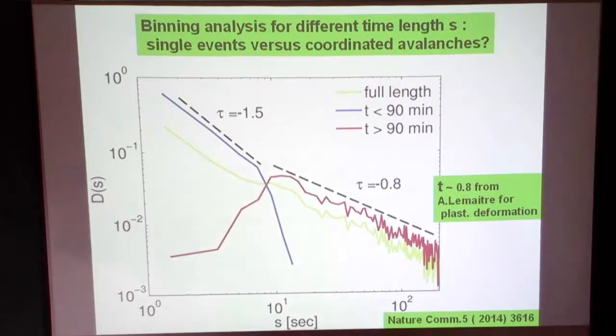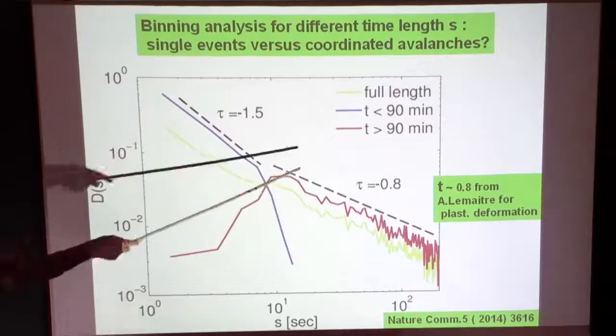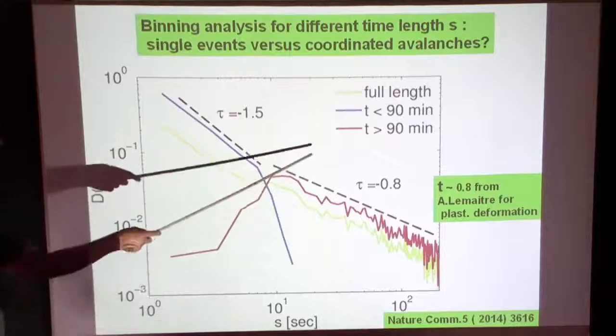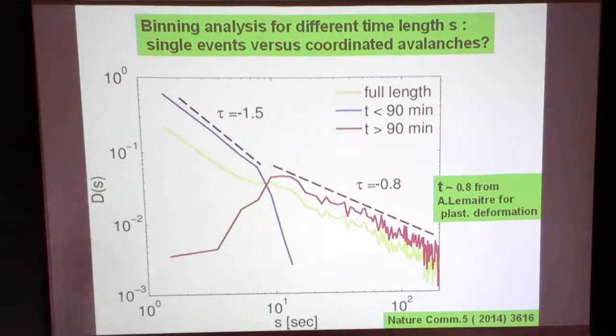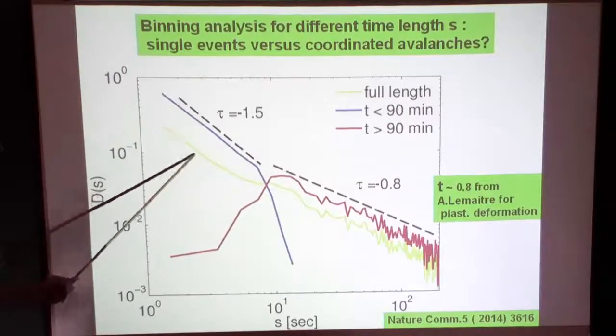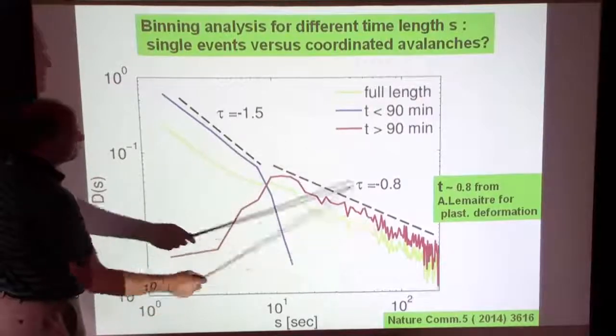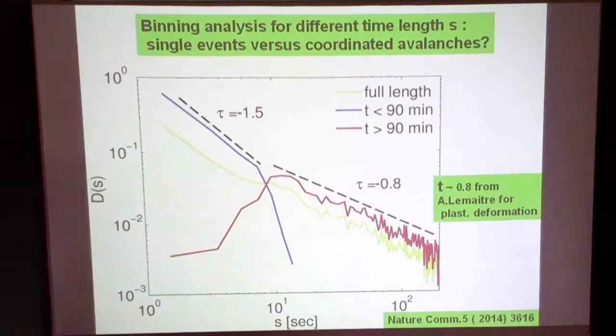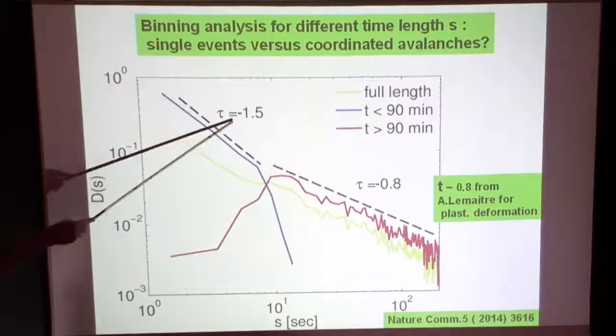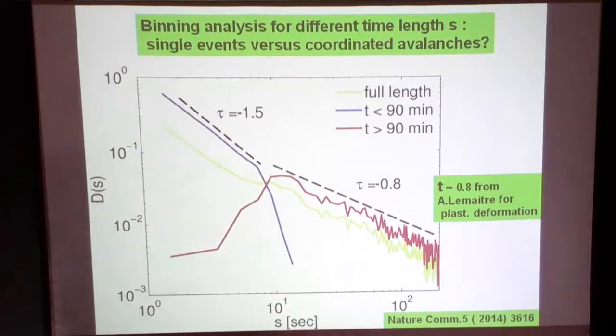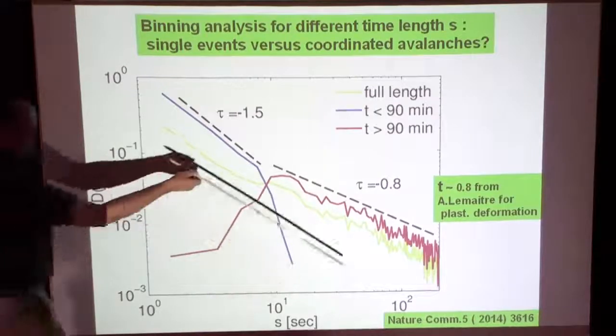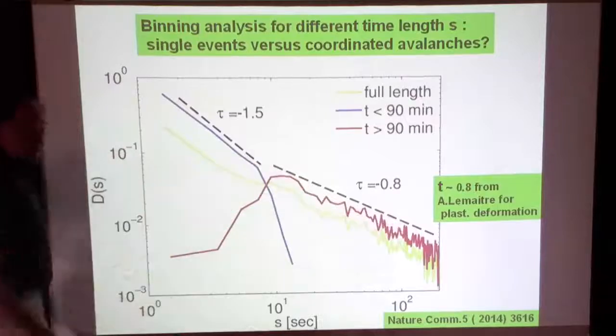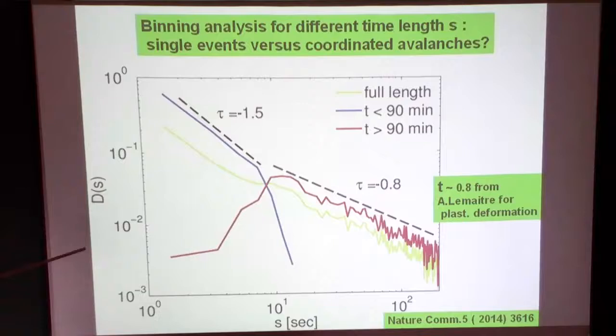Okay. Now we went up a bit higher in temperature, closer to the glass transition temperature, and what we observe here is what we think is a kind of crossover from one type of deformation to the other one. Again, this 90 minutes is just a number for this temperature. The temperature is not even shown here. So what we see is, again, a full curve of all our results, and we split it up into 2 different ones, the blue and the red one, more or less artificially, where we think the plots are going. In the very beginning, we see again this minus 1.5 or 1.4, whatever you want to call it. That's around the same number. But we see a clearly different deviation from that power law, for long waiting times, near the yield stress, near the glass transition temperature.